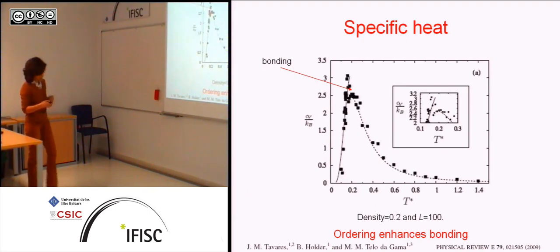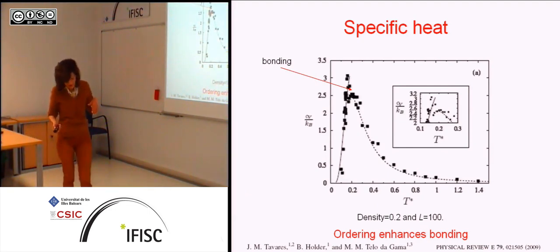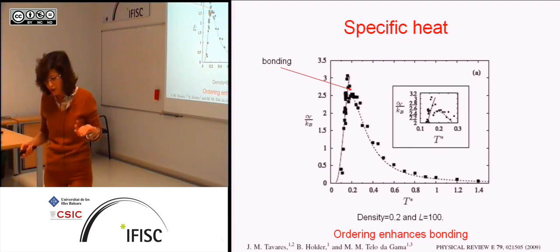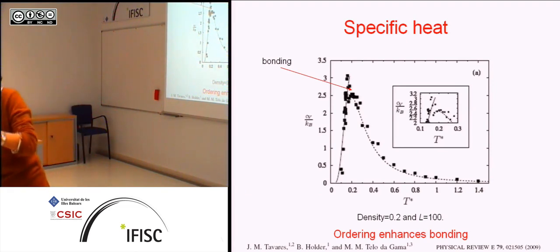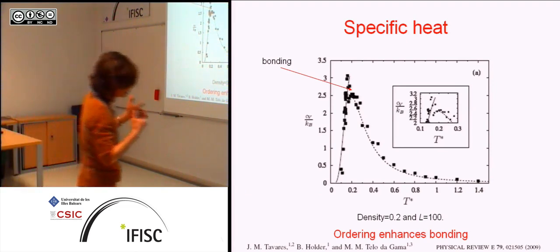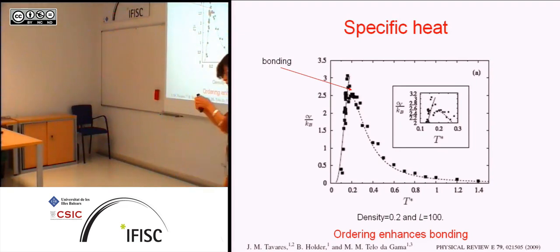So you can calculate the things. In these days we were interested in finding if we could see a signature of the self-assembly process, and this would be signaled by a maximum in the specific heat when the bonds start forming, even before the transition. At certain densities, you can actually see a bump in the specific heat before the system phase separates. So this comes from the bonding. And then the lengths of the rods have to grow sufficiently before they actually want to order, before they want to form the nematic phase.